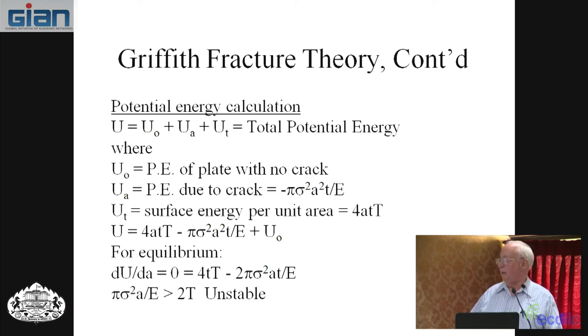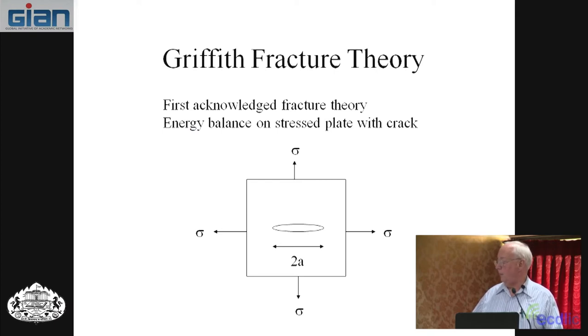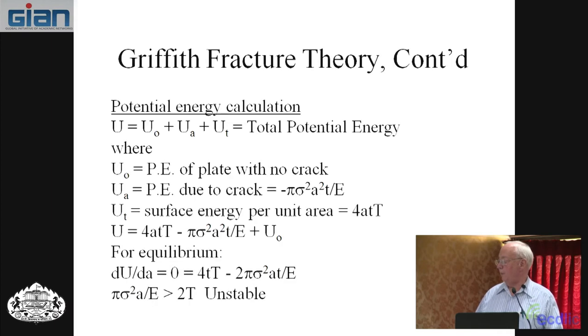And notice that the potential energy due to the introduction of a crack is negative. So if you start with this potential energy and introduce a crack, the total potential energy goes down. And then the other energy term is the development of new surface. So the surface energy term has this: 4A times T times capital T. Capital T is sort of a surface traction term. 4A because you have 2A crack length and you have a top and a bottom. So you have a top surface, a bottom surface, and a thickness gives the total area times the surface traction term. Then if you add them all together, you get total energy like that.